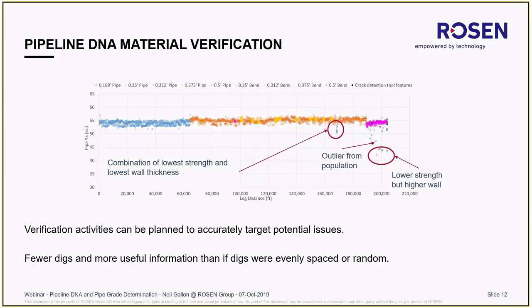Other things that we can pick up from here is a different line, and you can see that the vast majority of that is a very consistent, very tight distribution, just under 55 KSI yield strength. In this particular case, there are some areas which are lower strength. The two different areas that we have here of potential concern: the lowest strength pipes that we've measured are at about 200,000 feet, and they are somewhere under 45 KSI yield strength as measured.